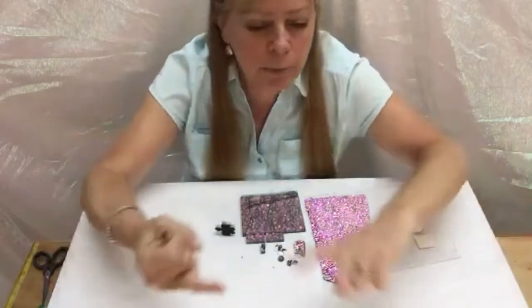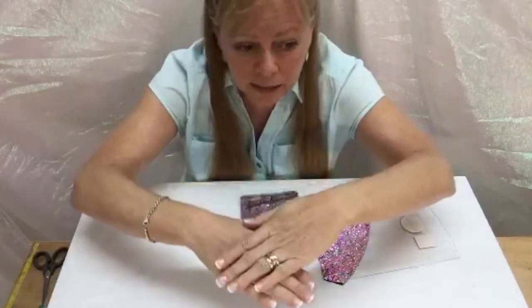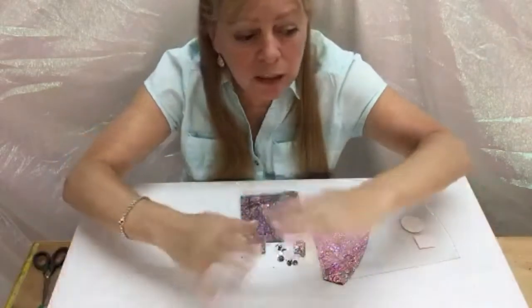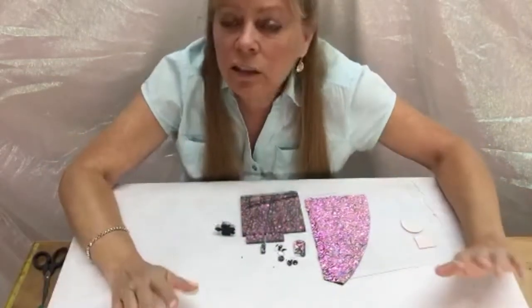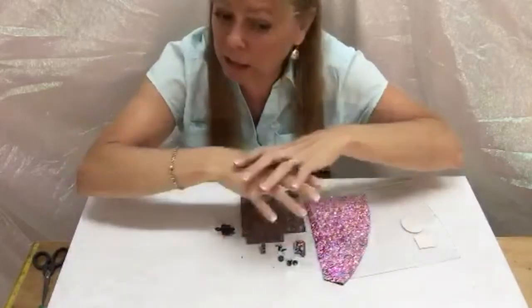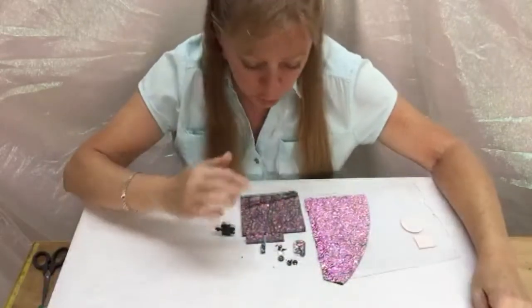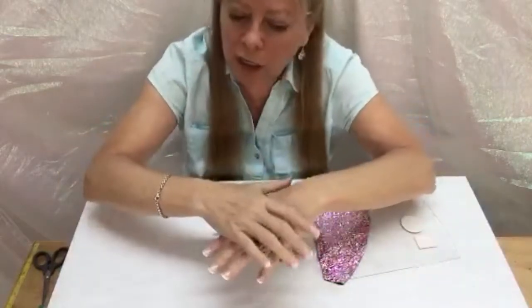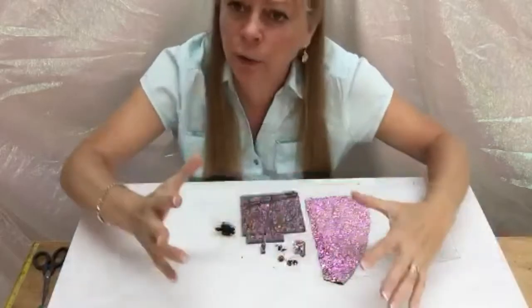What are some reasons glass can explode? One is incompatible glass — you put two different types of glass in the kiln and they can explode in the kiln or they can explode later. We don't want either one of those, so don't do that. Heating it too quickly — if you heat a large piece of glass too quickly, it can crack, kind of explode. Trapped air — if you get air trapped in the glass, it can explode or at least create a horrible bubble.